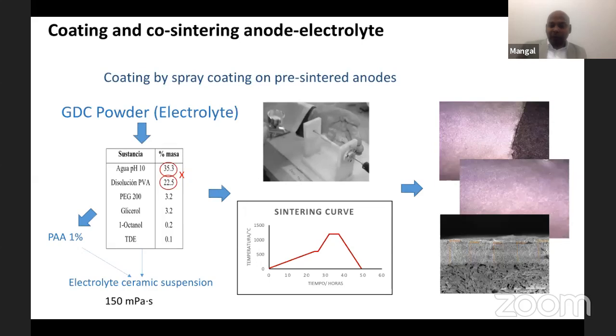So after that we coated the electrolyte. As I mentioned initially, it needs to be a very thin coating, but at the same time we need a highly dense coating. It's around 8 to 18 micrometers. So for that we have to carefully adjust the composition of the slurry. We needed many trials, and finally we achieved a highly dense as well as very thin coating by optimizing the composition of the slurry. So that is composition adjustment as well as the homemade spray.